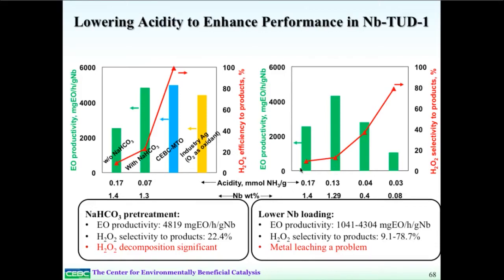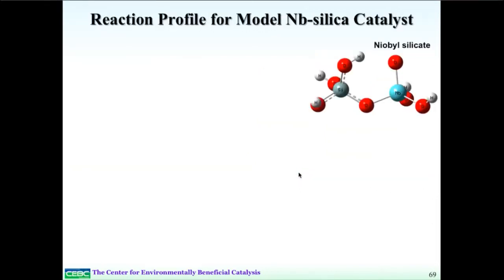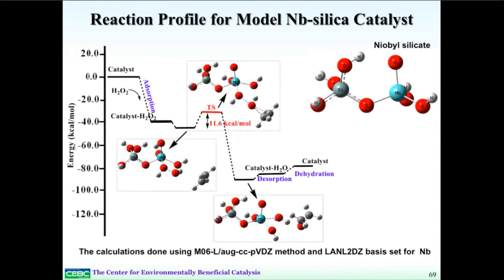So we've done a number of studies. Here, this is an example starting with a fragment of niobium silicate, a small-scale model of our system. We can map out the reaction pathway, starting from the system with the catalyst, adsorption of the hydrogen peroxide, adsorption of the ethylene. Here, there's a transition state, and then you end up with the product, which then you get desorption of water, and then you get desorption of the product, and then dehydration to form the original catalyst back.